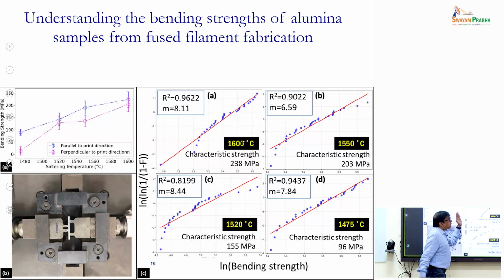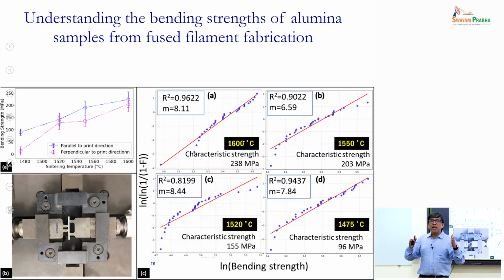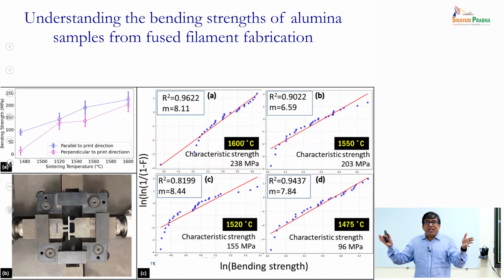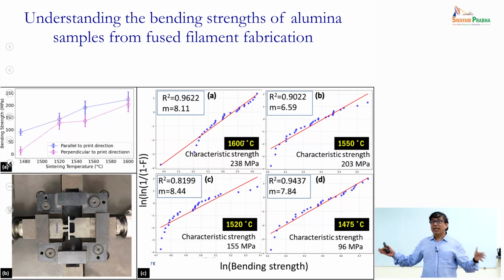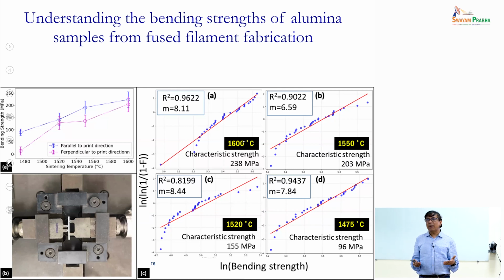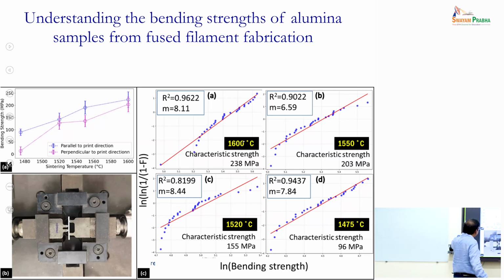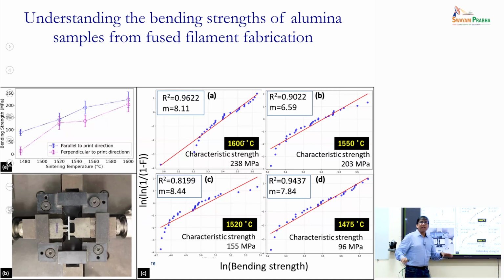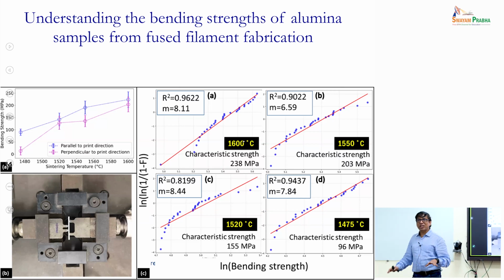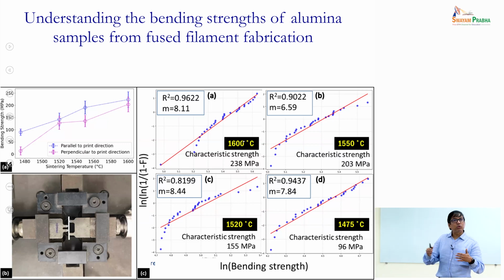So the Weibull modulus gives me an idea of the variation in the strength, whether the variation in the strength is narrow or broad. That has to be established. So it's very, very important to understand the Weibull statistics and get a Weibull modulus if I have to trust your data. Typically for ceramics, an acceptable Weibull modulus should be at least, I would say, 10 and above. We have not got 10. As you see, the highest value we got is around 8.44. Not bad for an additive manufactured component, but I would have loved to get more than 10.